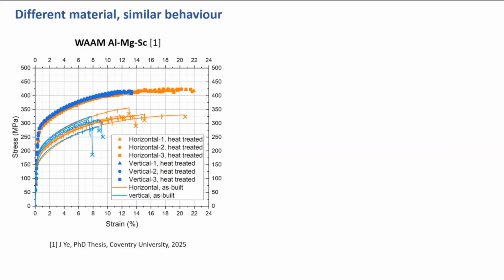So just to say, when we change to a different material, we found similar behavior. This is an aluminium magnesium alloy with scandium, 0.3% scandium. The reason for adding scandium is to make it stronger, for space applications. And this is from a PhD student I supervised who just submitted. So the lower curves are without heat treatment, the upper curves are with heat treatment. But as we say, the strength never has any problem. It's always okay. It's the elongation at failure. Very large scatter also depends on whether there's porosity or not.